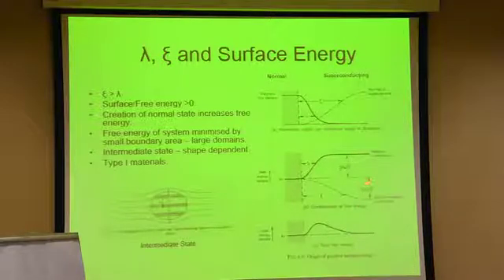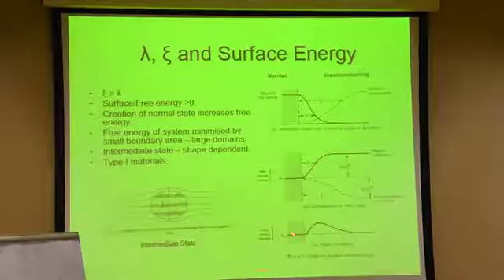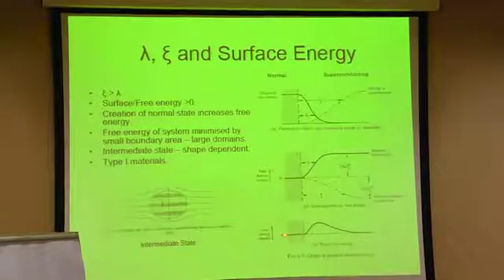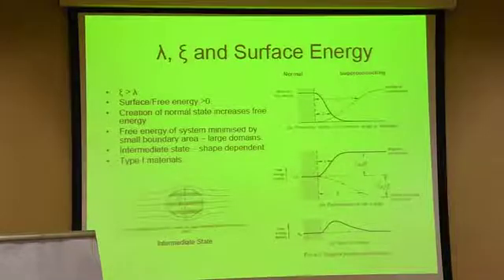From the free energy discussion of the critical temperature and so on, these two parts are equal. So this is the condensation energy which equals the magnetic contribution. Deep inside the superconductor, this goes back to zero. And if we add these two, we have this thing. So the free energy of the normal, the free energy of the inside, because we have the Bose-Einstein condensation, but at the surface, what we see here is a little region in which the free energy has a maximum. What does it mean? It means the system will hate to have interfaces between the superconducting and normal phase. But if you are forcing it to have also normal phases, what we'll do, we'll try